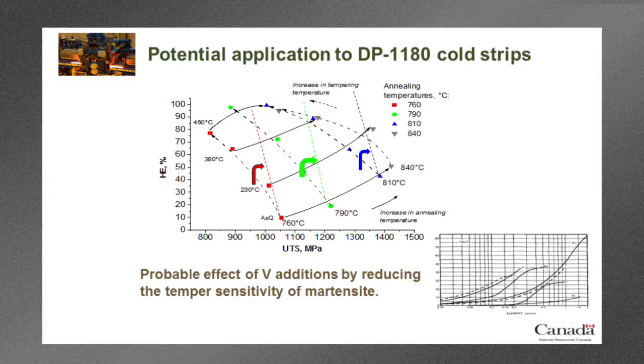So we'll improve the hole expansion coefficient significantly, but we'll soften the steel as well because we're essentially tempering the martensite. If we added vanadium, then vanadium has a very well-known effect. It reduces temper sensitivity of martensite. That can be seen on the graph on the right. I won't go into this in detail. I can give you a reference later on. It's a well-known property of vanadium that it actually reduces the softening of martensite during tempering.